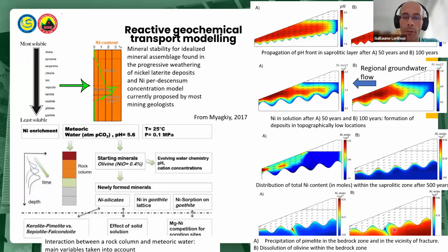So in the context of plateau slope deposits, the simulation suggests that the most nickel-rich zones in saprolite form usually where limonite is thin or absent, while the areas with lowest nickel are located in topographic highs under the thickest limonitic cover. Therefore, understanding topography, slopes, shapes of bedrock contacts, and localization of preferred fluid flow paths is critical.